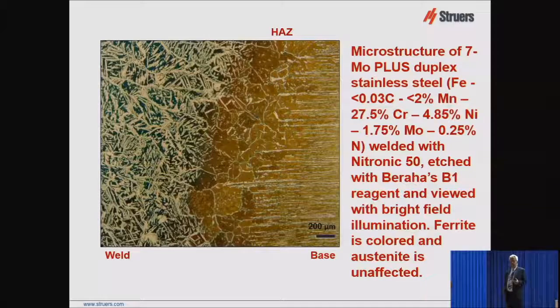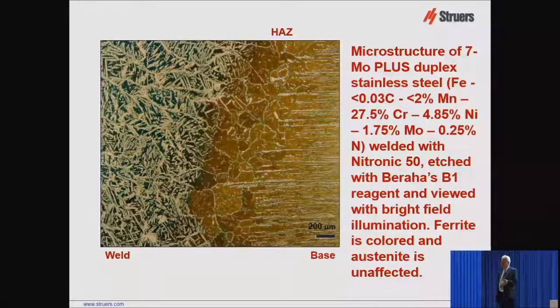And people were talking about how austenitic stainless steels are so wonderful, great properties, great corrosion resistance, except they have this one Achilles heel: they're sensitive to chloride ion stress corrosion cracking. And this is a serious problem with austenitic stainless steels in some environments. But on the other hand, you have ferritic stainless steels that are totally immune from chloride ion stress corrosion cracking. However, they're not ductile. They're BCC. Face centered cubic metals, austenite, are much more ductile. And so somebody said, well, maybe we could marry the two phases and get the best of both worlds.